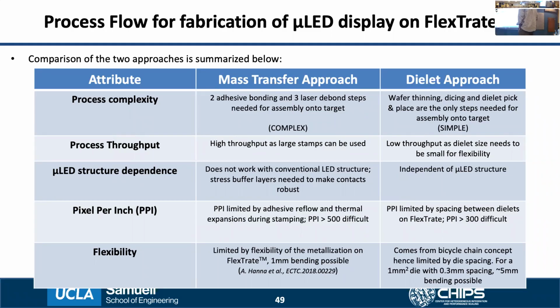In the case of the dielet approach, each individual sapphire dielet can have any PPI because it's really defined lithographically. But then because the dielets have to be separated by a certain inter-dielet spacing to account for flexibility, PPI greater than 300 would be difficult in this case.